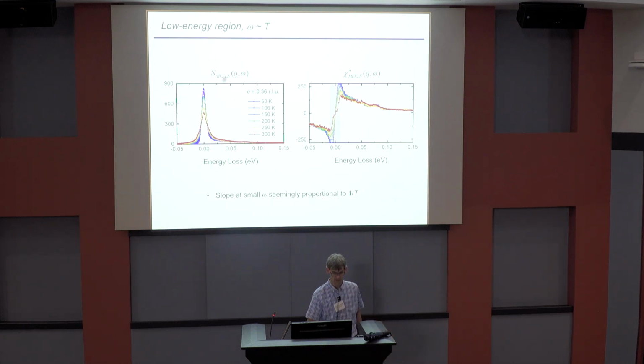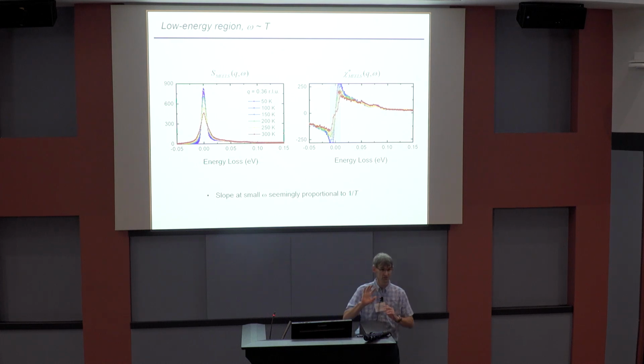Another way to view it is to take S and anti-symmetrize it to get the susceptibility, which will then necessarily be odd. And you can see that it looks like this. The gray shows the region, just to be honest, where the resolution is really important, and I don't absolutely trust the results. But the bottom line is there is a thing in here with a slope, and the slope changes with temperature. At lower temperature, it gets more steep. So it looks consistent with a linear omega slope with the slope 1 over temperature, which was what the original marginal Fermi liquid hypothesis suggested. Let me show you some better data.